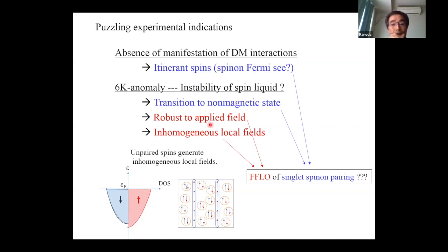And this is very robust against magnetic field, and at the same time, inhomogeneous local field occurs. So these puzzling features may suggest, to a simple-minded person like me, an FFLO state of the singlet spinon pairing. And this 6K anomaly may suggest the occurrence of spinon pairing. And this anomaly is very robust against magnetic field. And the generation of inhomogeneous local field is consistent with the emergence of the FFLO state.